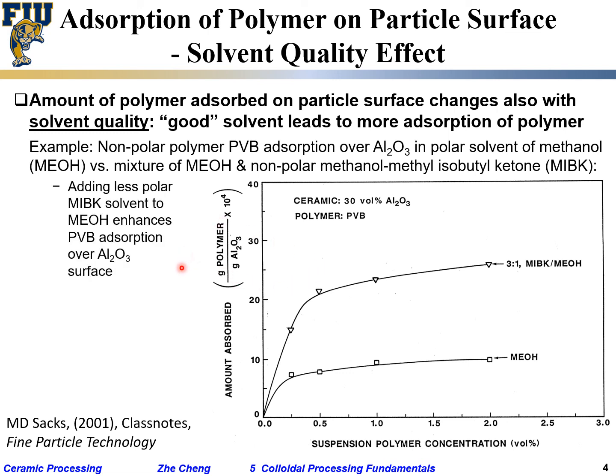So that's what we said. Less polar MIBK added into the polar solvent. We are making better interaction between the solvent and the polymer, and as a result, we are promoting the polymer adsorption onto the ceramic particle surface.